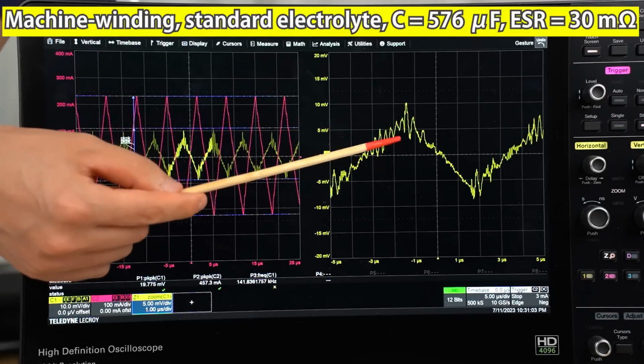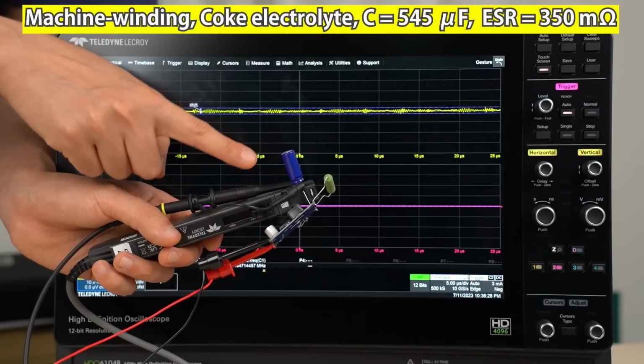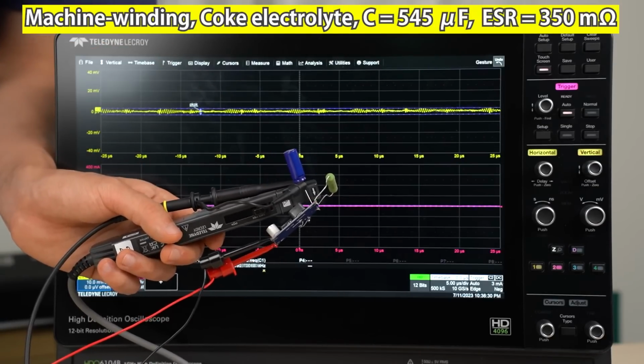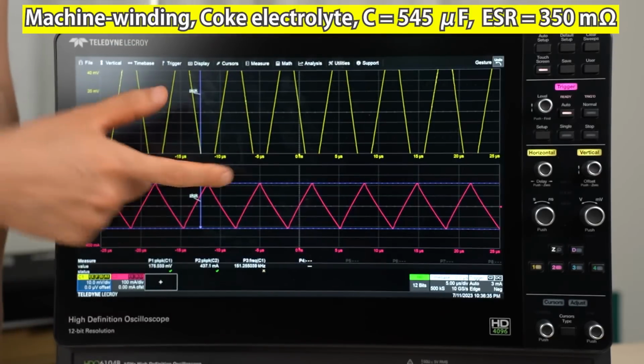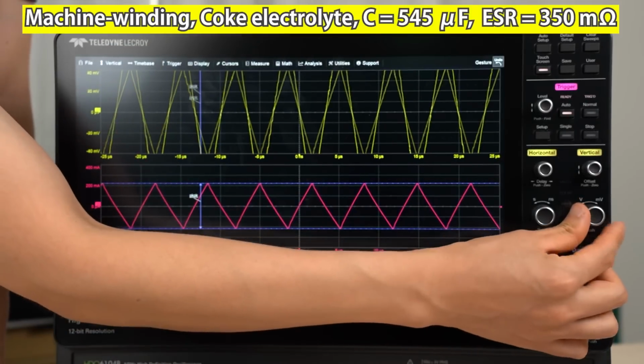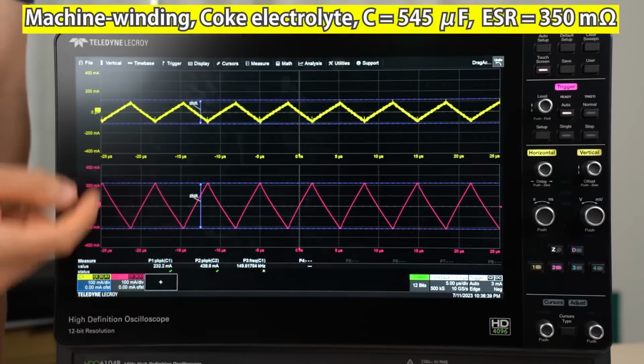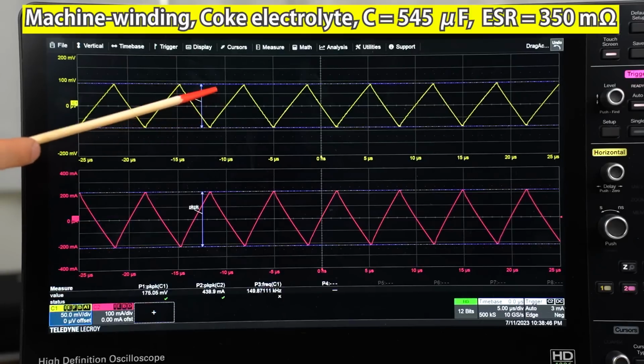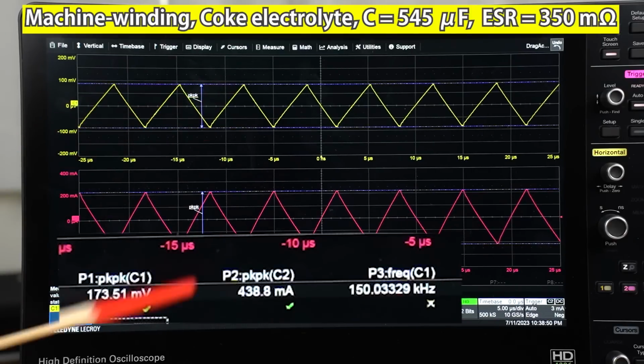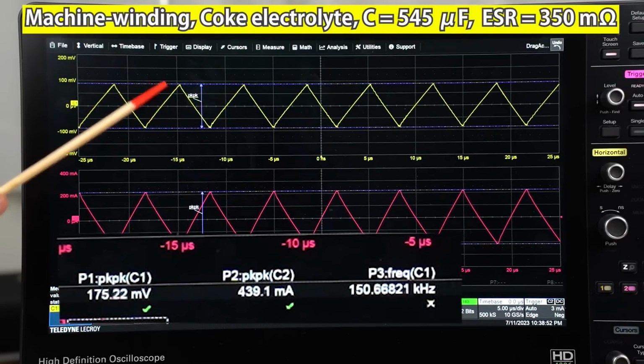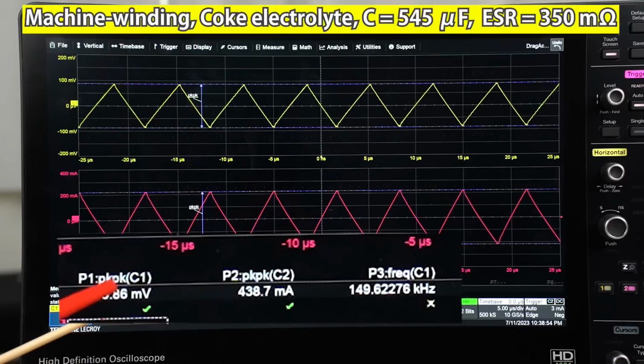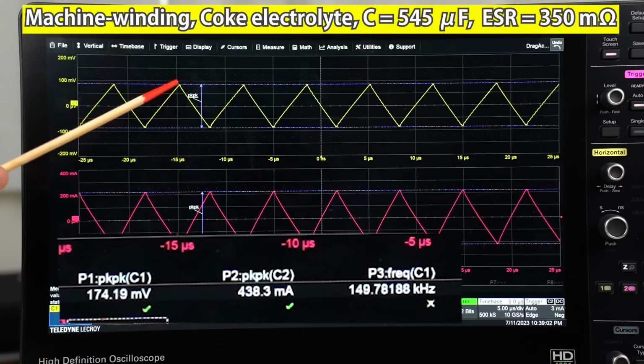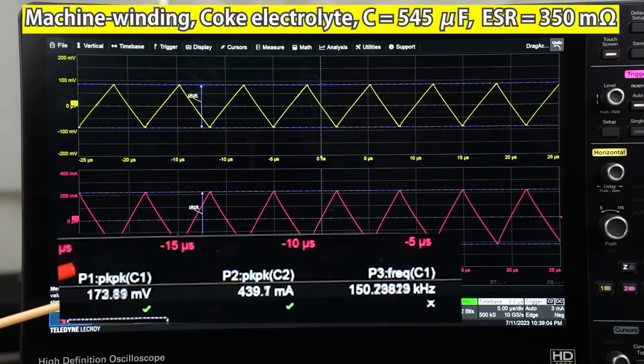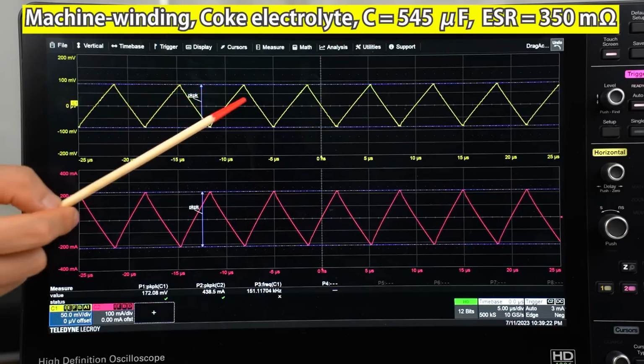ESR has more influence. Lastly, the machine winding capacitor with Coke electrolyte. I turned on power. Well, the ripple voltage doesn't fit in the display. I'll adjust the range a bit. There you go. Coke electrolyte causes huge difference. The standard electrolyte capacitor has about 20 millivolt ripple voltage peak to peak. The Coke electrolyte one has 170 millivolt ripple voltage peak to peak. The ripple voltage is about 10 times higher.